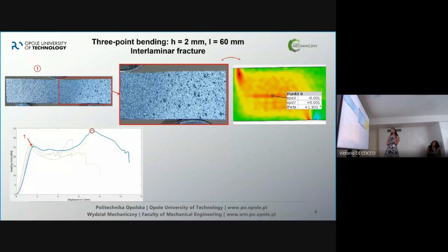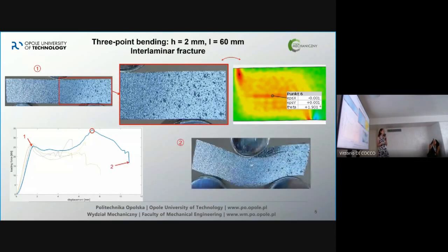And you can see there is delamination like every 2 millimeters or something. So between the layers, we started to have a delamination which was not visible before.